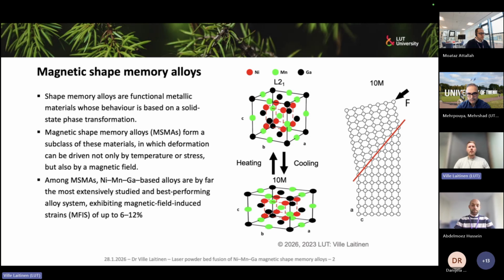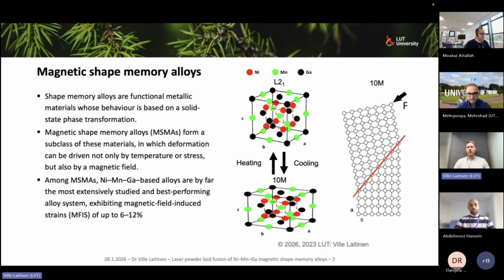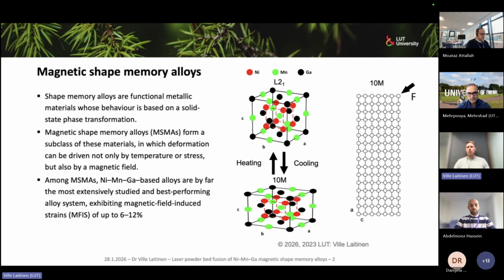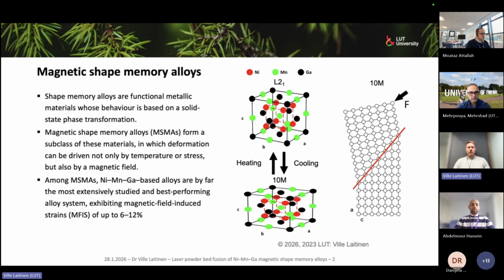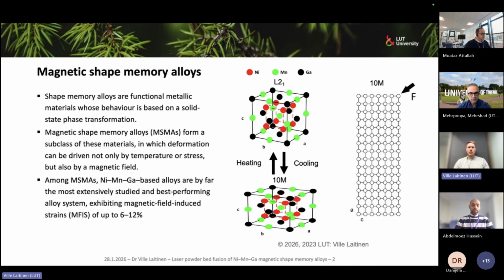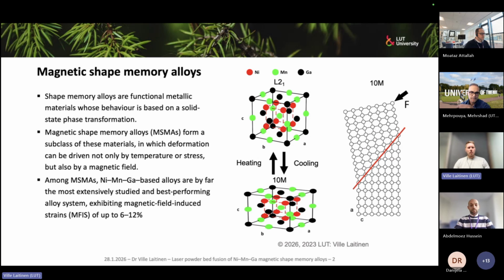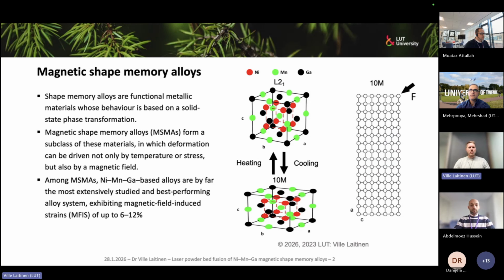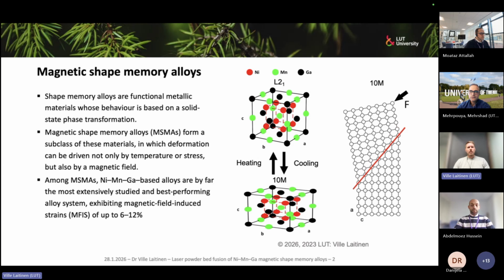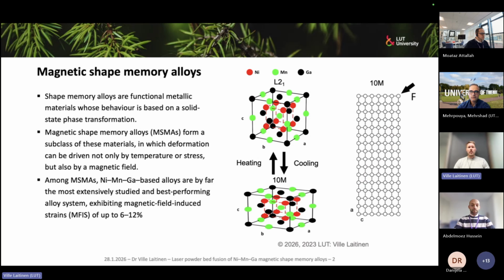Conventionally, the shape memory effect is used by heating martensite to higher temperature austenite, so you can recover some previously trained shape. Or if you have a superelastic alloy, by stress-induced phase transformation from austenite to martensite, you can have local plasticity, and then by removal of the stress, you again have the shape recovery. Now, in nickel manganese gallium in particular, which is one of the most used and well-known magnetic shape memory materials, we have also a third phenomenon going on. This is called the magnetic shape memory effect, which can produce approximately 6 to 12% magnetic field induced strain.